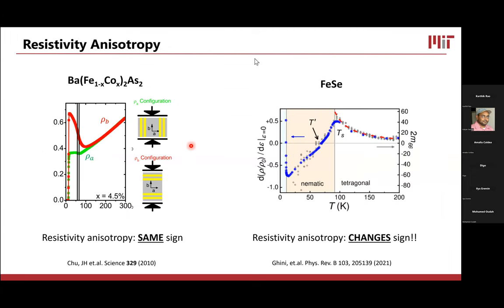Then we have to talk about the resistivity anisotropy. So to my knowledge from the papers I've read on the iron pnictide superconductors, when you put them under pressure and you measure the resistivity anisotropy below the nematic transition, whatever sign that the resistivity anisotropy has, it maintains that sign through the entire temperature range.